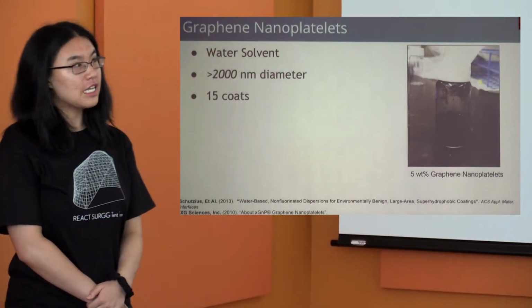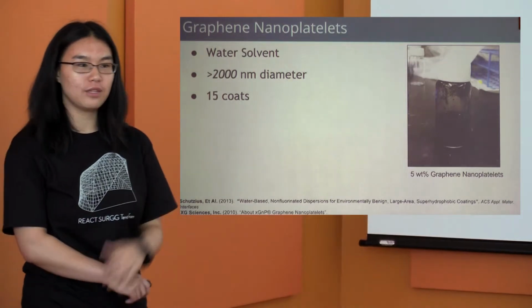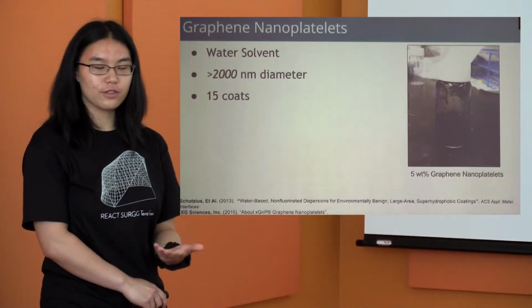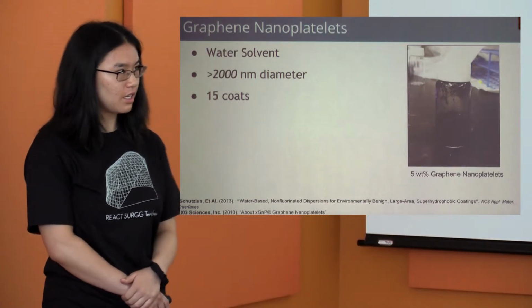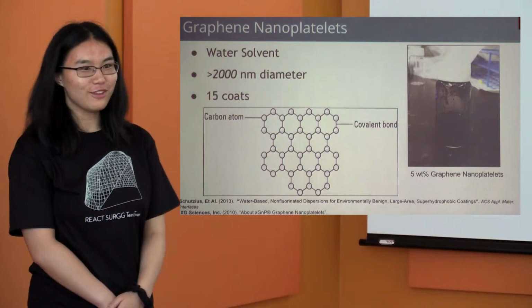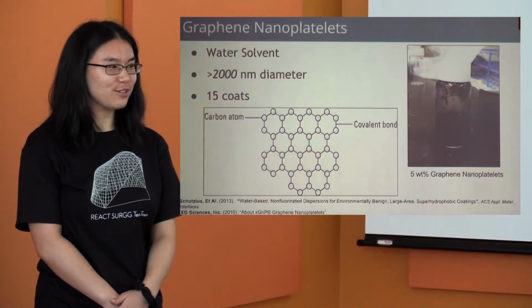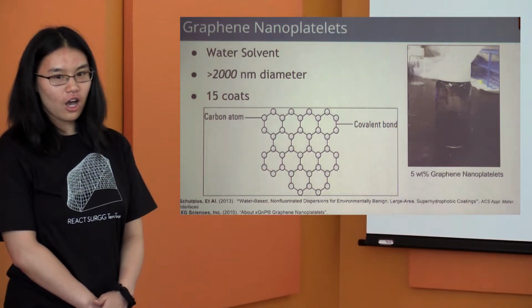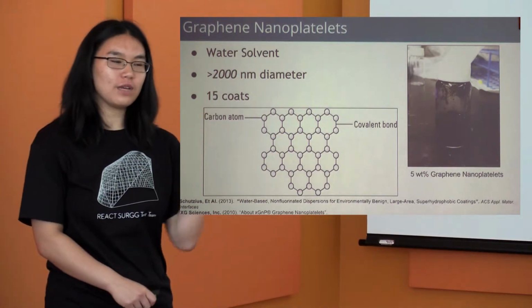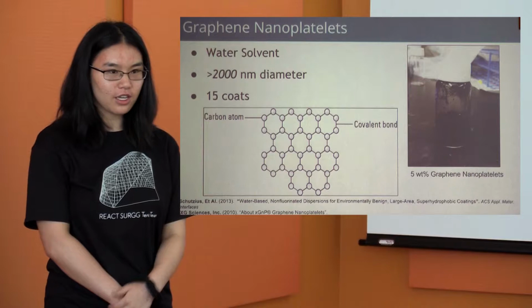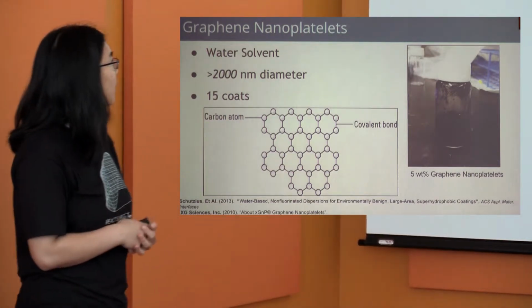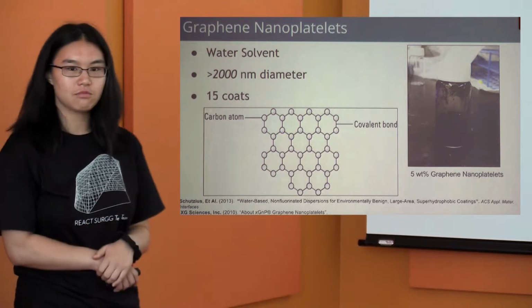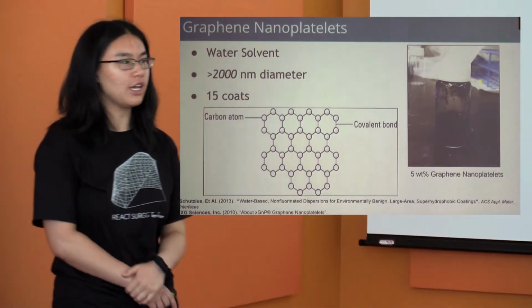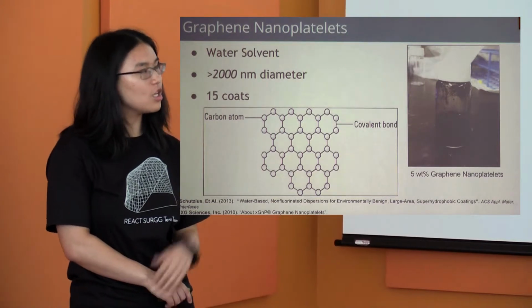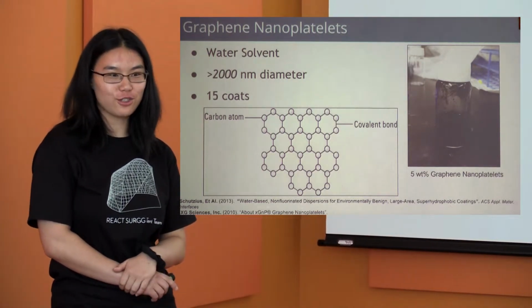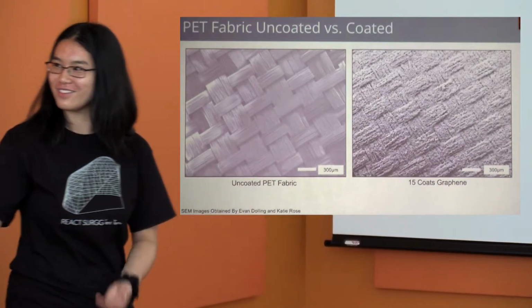something that we obviously want as a tent. Now for our actual spray, we chose graphene nanoplatelets. This is due to the fact that they are water dispersible, which is something that we did want in order to make it friendly for the environment. Furthermore, it's just a lot of carbon atoms, which is hydrophobic in nature because they do not have polar bonds. Furthermore, since these are platelets, when we actually disperse it using the graphene spray coating, it automatically has roughness. We actually found this in a paper that suggested it to us, and we then built upon that and found that 15 coats was the appropriate thing to deposit on the platelets. So without further ado, I'd like to turn it over to Sisan to show what these actually look like.